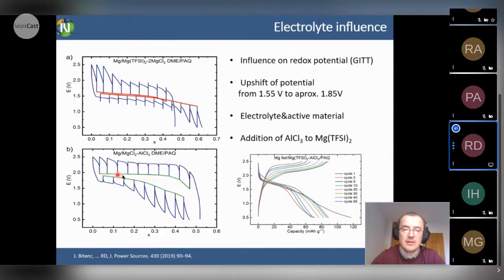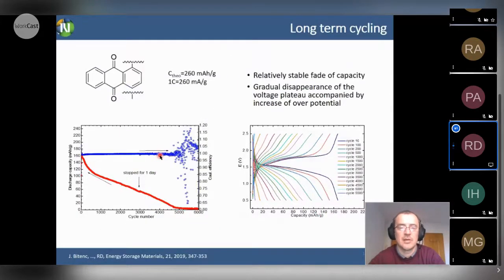that adding aluminum chloride into the electrolyte solution actually increases the operating voltage. So you can see here that using this GITT, we were just curious where the thermodynamic stability is, or where this OCV voltage is, and the difference is like 0.3, 0.4 volt, and this is a significant difference, which is actually contributed by aluminum chloride, which shifts the electrochemical potential of the quinone group. And then this electrochemical potential of the quinone group can be shifted again by designing ortho, para, meta positions and so on. So there is a lot of different area to play and to adjust, and of course then to bring this technology to a better solution.